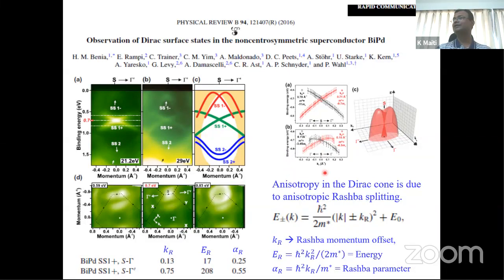Like here it is shown that for one K vector it looks like this, and for another K vector it looks like this. So the spin splitting of these states at a particular K point is different. This anisotropy is probably coming from the anisotropic Rashba effect. That's what they think, and they have modeled this. So this Kr is the Rashba kind of term, which is anisotropic in different K directions. That's the explanation that they gave.